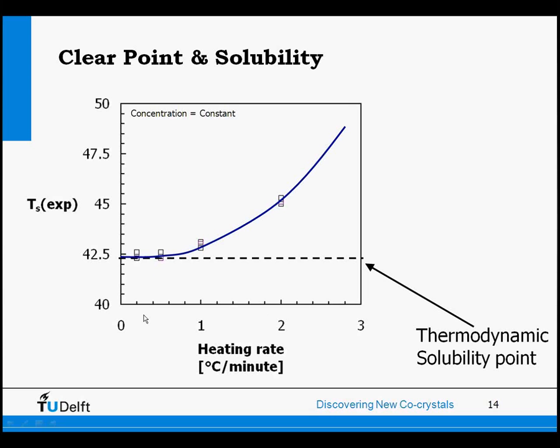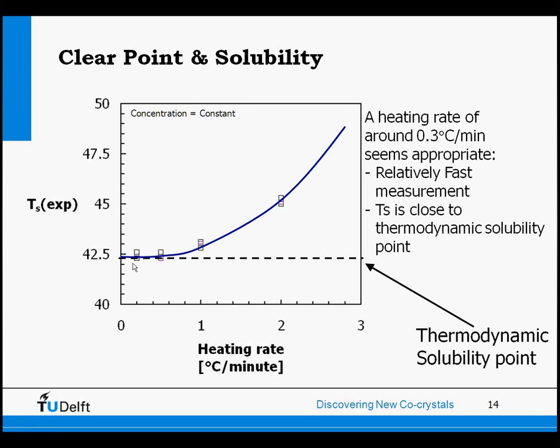There you see that the crystals get enough time to dissolve when you increase the temperature. So upon decreasing the heating rate, you get closer and closer to the thermodynamic solubility point, and that is actually what you want to know, the thermodynamic solubility point. So with a heating rate of around 0.3 degrees Celsius per minute, we have a relatively fast measurement, and our saturation temperature is close to the thermodynamic solubility point. So usually we use a heating rate of around 0.3 degrees Celsius per minute.